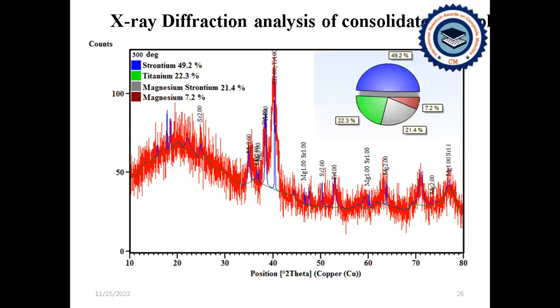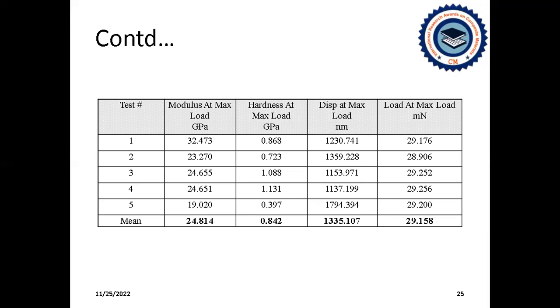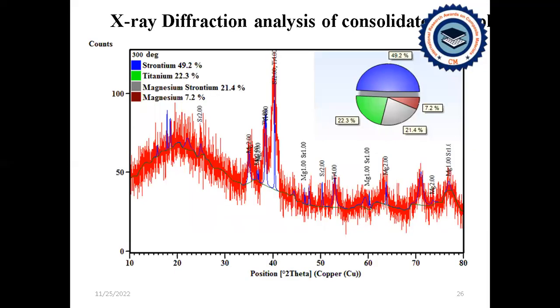Hence, in our present investigation, we got a low modulus value of 24.5 gigapascal when we compare it with other titanium based alloys, and this alloy is found to be most favorable for biomedical applications as an implant material.